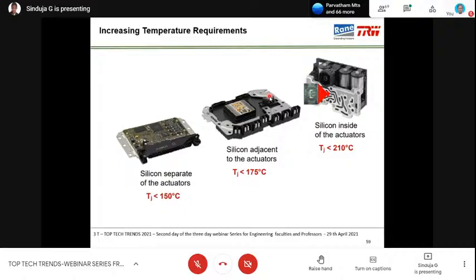So in this slide, you can see three different topologies. The first one is the remotely mounted ECU, in which the silicon is separated from the actuators. So the junction temperature TJ is nearly 150 degrees Celsius. In the second topology, the ECU is fitted adjacent to the actuator. Hence, the junction temperature of the semiconductor can rise up to 175 degrees Celsius due to the heat radiation from the actuator. In the third topology, the ECU is built inside the actuator, so the junction temperature rises as high as 210 degrees Celsius due to the direct heat conduction and radiation from the actuator.